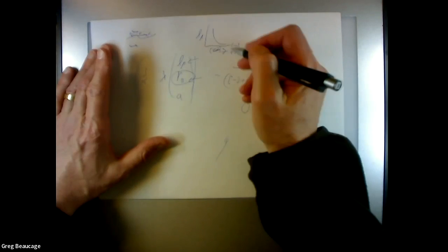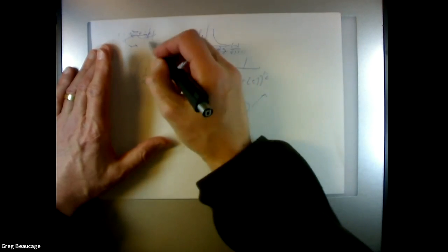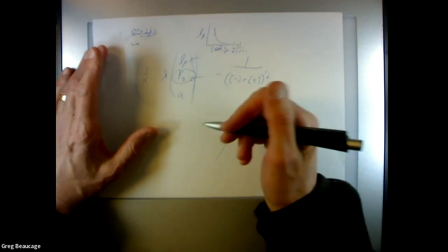So the persistence length gets smaller as the counterion concentration increases because the Debye screening length gets smaller. So the long range charges disappear. And then you only see the local ones, so it becomes more flexible. If that happens, then that could explain some of the things he sees too. Like he doesn't consider the Debye screening length changing. The A is fixed. This thing changes with Z.